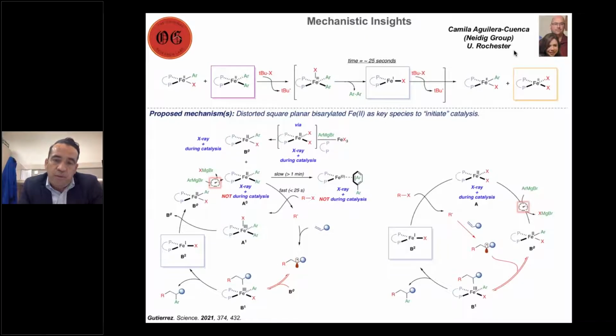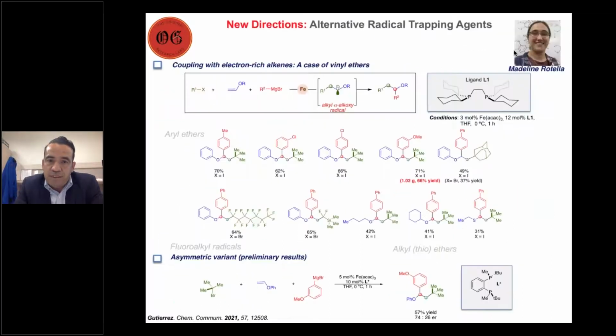And we also cannot rule out the other pathway shown on the right, where presumably an iron(I) species is responsible for halogen abstraction to generate an iron(II), and that could perform this catalytic cycle. So we're still continuing exploration of this mechanism. Again, we want to differentiate: do we have the mechanism shown on the left, or the mechanism shown on the right? Because if we have that kind of information, I think that will lead us to more rational design and new transformations. And as you can see here, this is not limited.